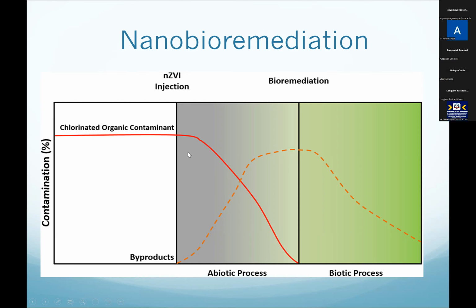increasing. So as I said, the chlorinated compound is decreasing, and due to that reduction of the chlorinated compound, you're going to get byproducts. Basically, you get hydrocarbons. Hydrocarbons come up, increase. So the chlorine is gone, and they have C and H. And then what happens is, now the microbes will like the environment. You don't have that toxic stuff around them, so then they become active, and they start degrading those hydrocarbons.